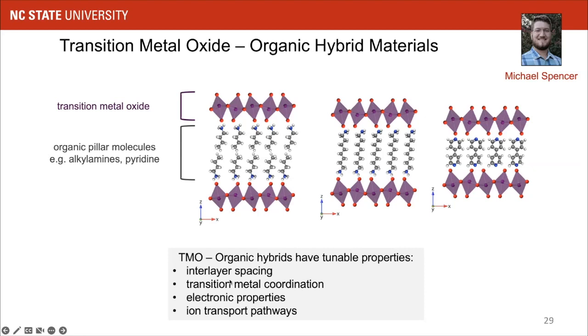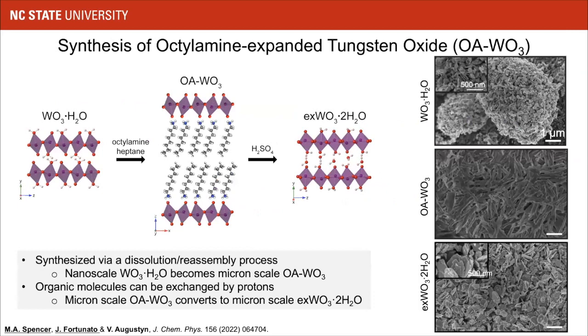The biggest one is interlayer spacing, but you can also affect the transition metal coordination, ion transport pathways, and so on. This is what the materials look like. In particular, we used our friend, the tungsten oxide monohydrate. You expose it to octylamine and heptane, and there's a dissolution reassembly process. So it's not just an ion exchange, but this material actually dissolves and then reassembles with the octylamine in between the layers. And we can see that through the change in the microstructure on the SEM from the nanoscale morphology of the monohydrate to the micron scale octylamine containing material.